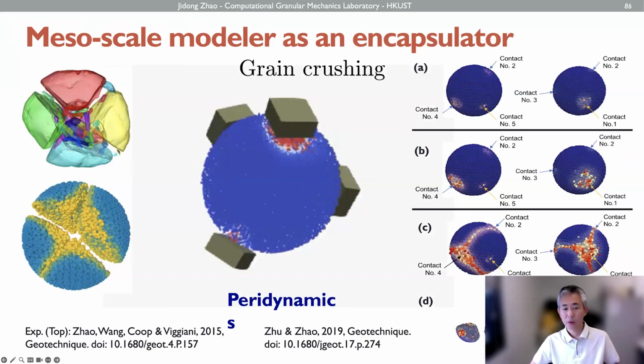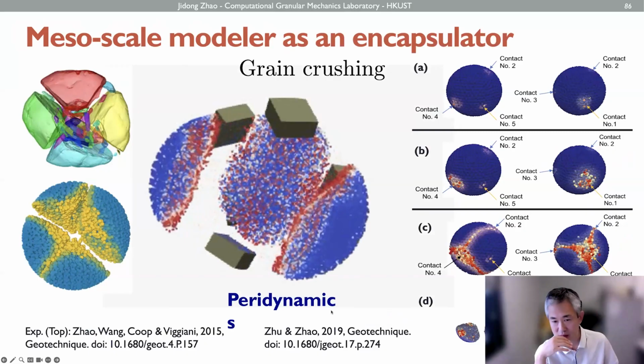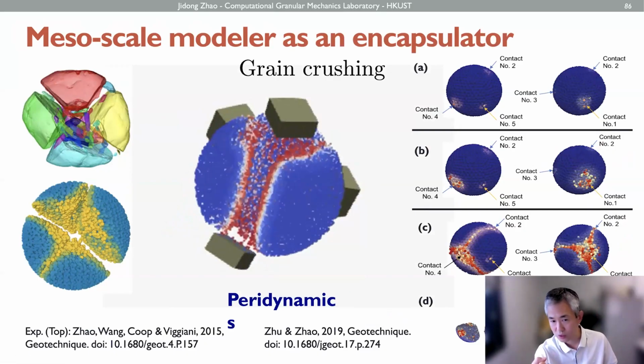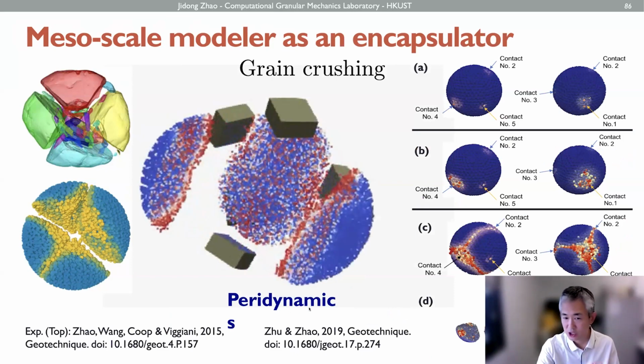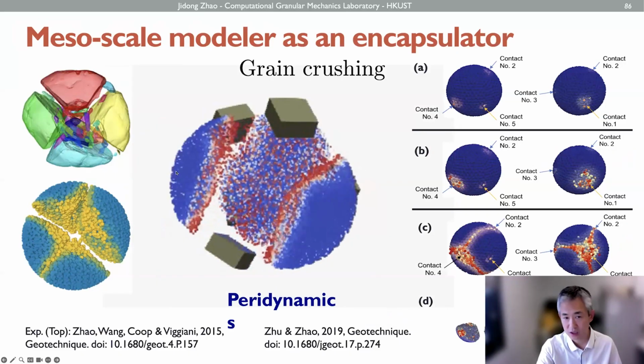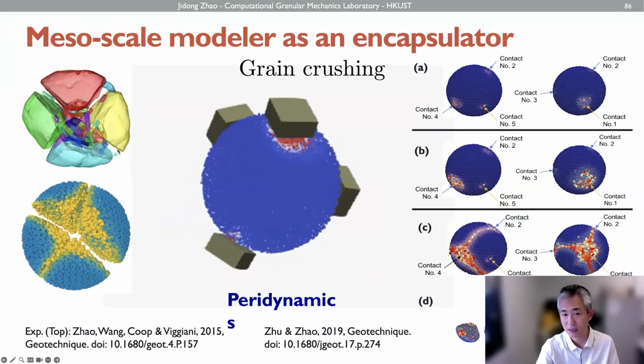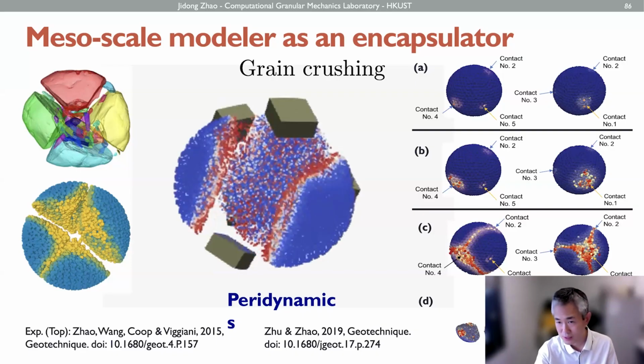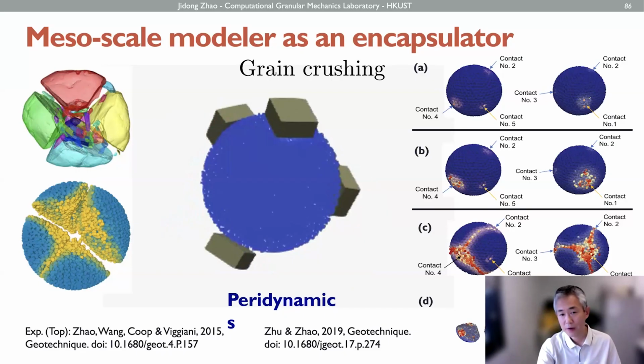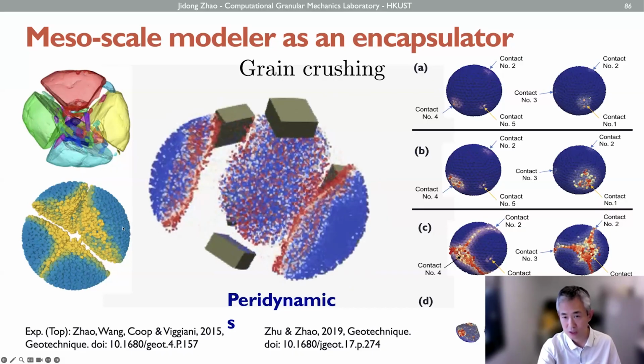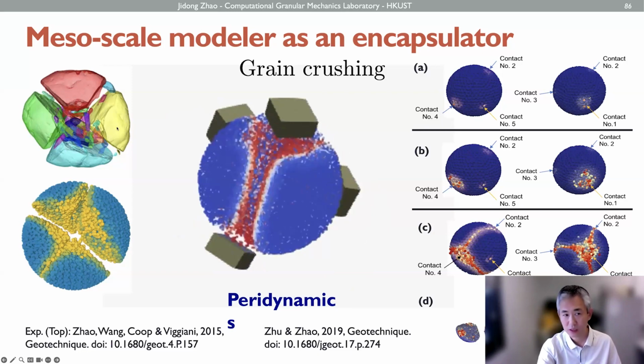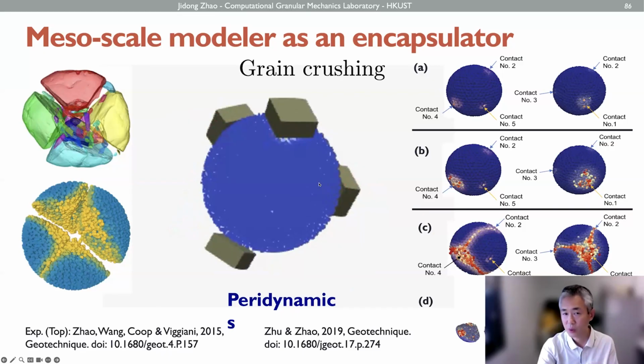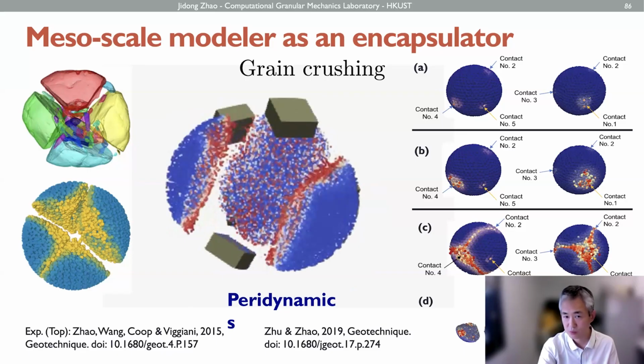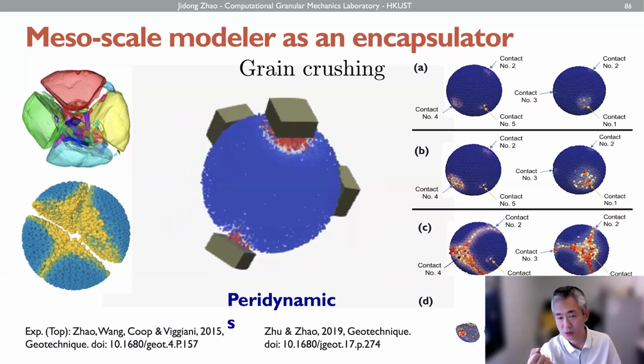So what we do is, we recently use a peridynamics method coupled with other methods to study the crushing. Peridynamics is a new non-local continuum-based method to simulate each particle like a bonded particle, but different. Material points basically interact through the bond. The bond can be specified with different models here. It's very efficient in solving these fracture, fragmentation, or cracking problems here. This is a simulation of a single particle crushing by this peridynamics here, and we compare it to the experimental observation here. And then essentially we want to incorporate this peridynamics into this particle crushing simulation in a way that this peridynamics can generate a more realistic crushing pattern in terms of the particle size and particle shape.